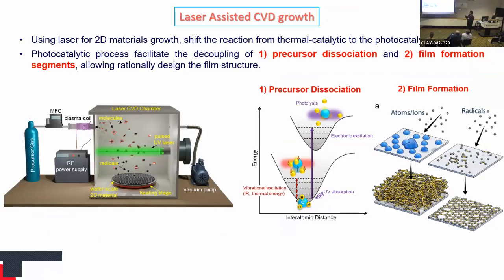This is the first time we grow using laser CVD. That is very different from the thermal CVD technique. In a normal thermal CVD process, we have high temperature, it dissociates and gets new species. In this case, we use laser. The laser energy is basically breaking the bonds between the molecules. So we are not using high temperature to break the bonds. It is a photolytic process that breaks the bond, and once you have active species, they can deposit on the surface and create a film.